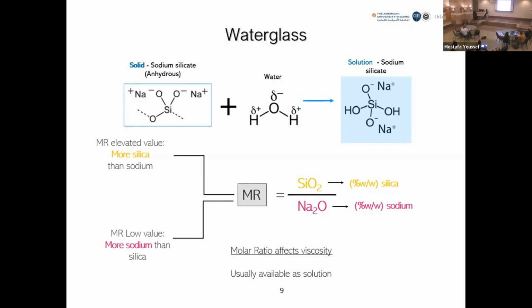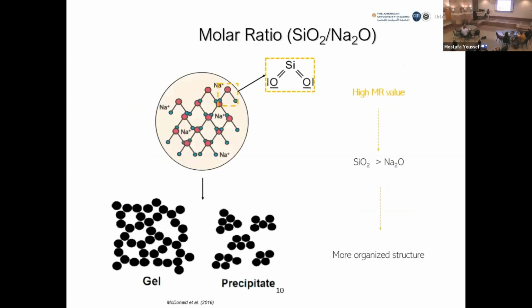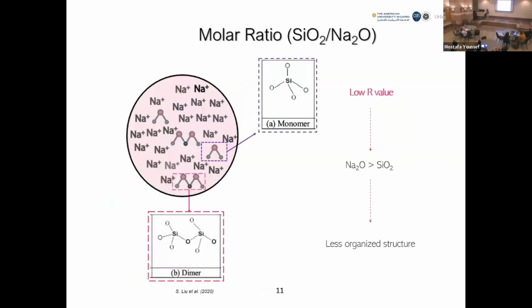How is the viscosity affected by the molar ratio? Here I reported the case in which we have a higher molar ratio, and this means that in our system we have a lot of SiO2 with respect to the sodium quantity. In this case the SiO2 starts to link together, and the structure starts to polymerize and is very well organized, and for sure in this way we have an increase in viscosity. Instead, if we have a low molar ratio, we have more Na2O with respect to silica, and in this way the creation of the network is reduced due to the presence of sodium ions inside the solution.